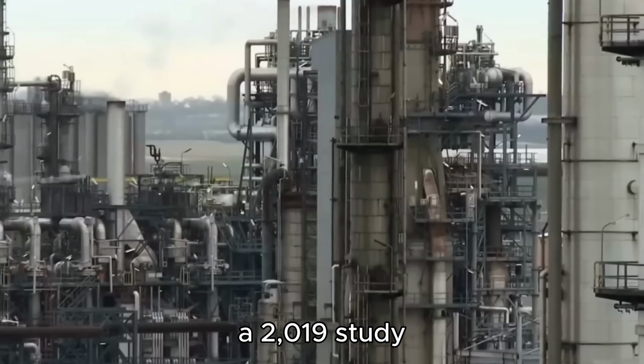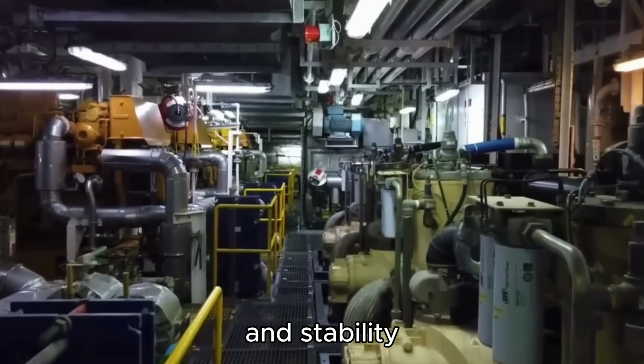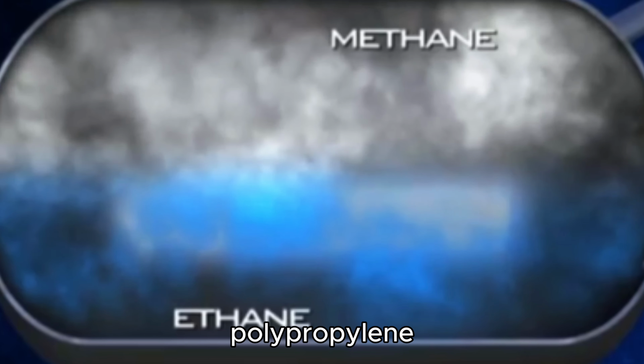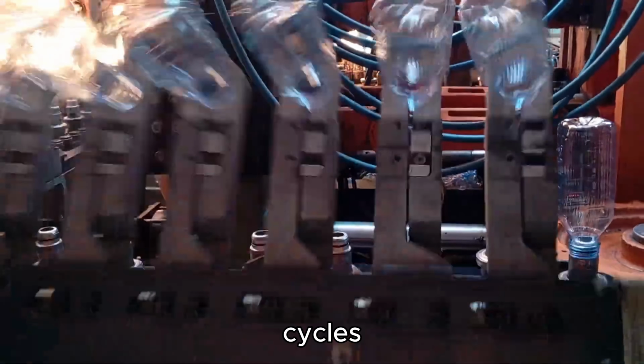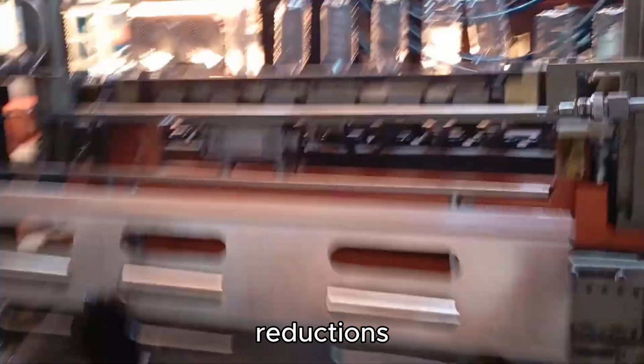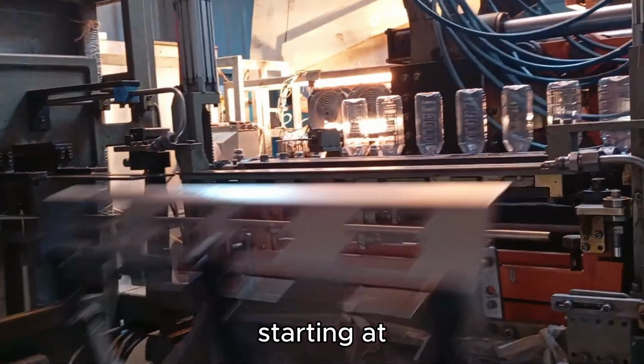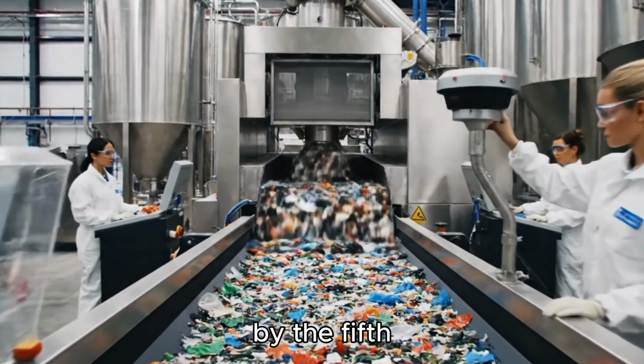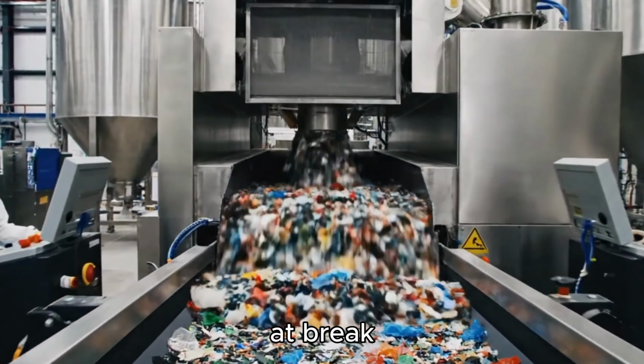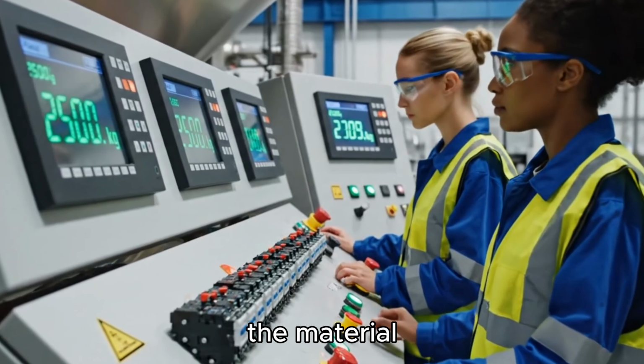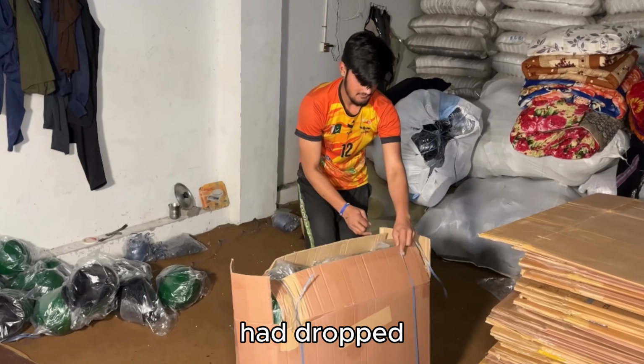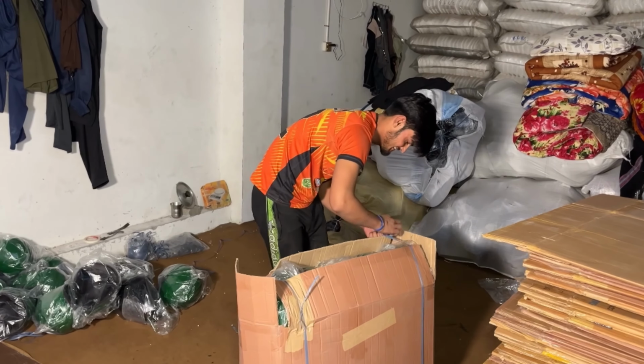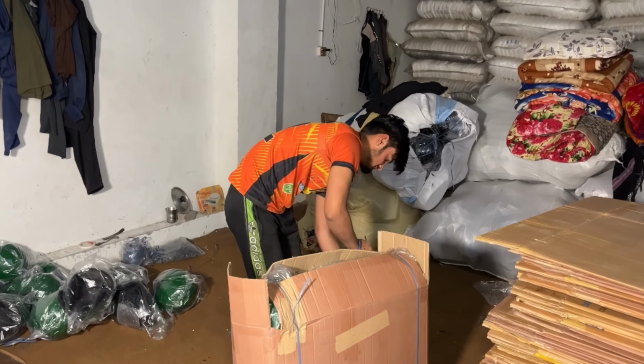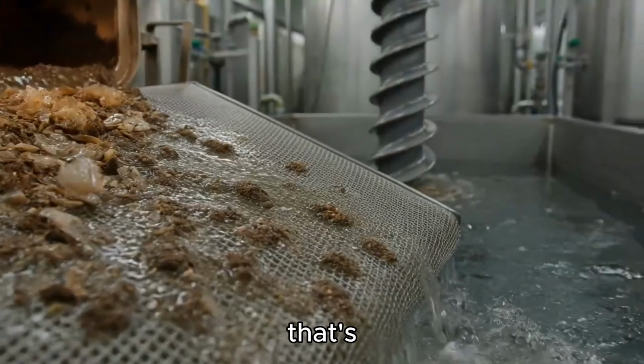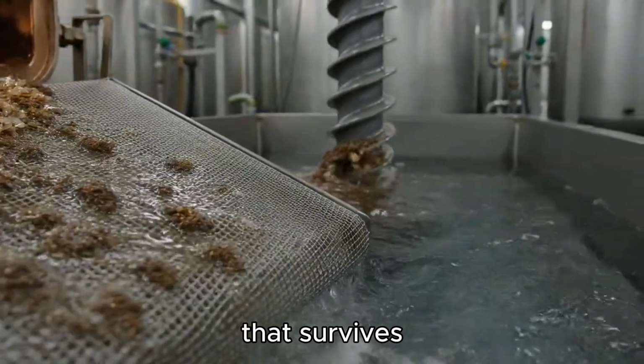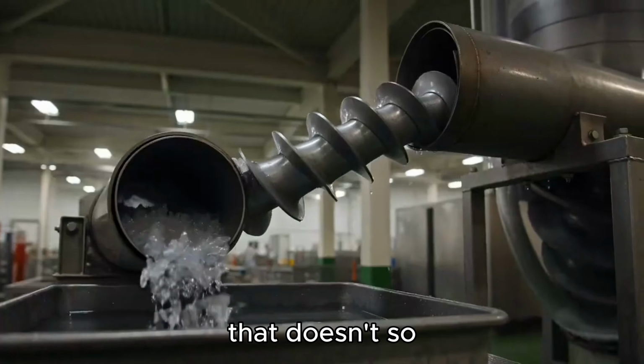A 2019 study in the journal Polymer Degradation and Stability followed polypropylene through multiple processing cycles and documented measurable reductions in impact strength starting at the 3rd cycle. By the 5th cycle, elongation at break, basically how far the material stretches before it snaps, had dropped roughly 40% compared to virgin material. That's not a rounding error. That's the difference between a car interior panel that survives a cold weather impact test and one that doesn't.